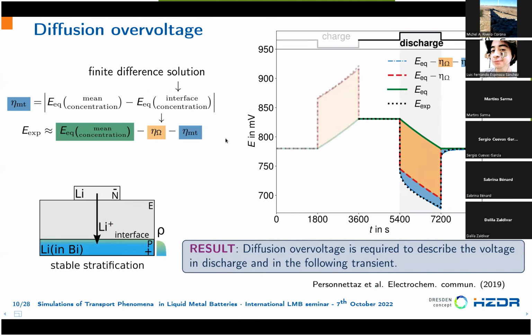Now, if we take the previous model and plug it inside our mass transport overvoltage equation, we see that we are able to capture extremely well the experimental behavior. So the three contributions, the equilibrium, the ohmic, and the mass transport, are able to describe perfectly what happened in the experiment. They are also able to describe the following transient. When the current is shut off, there is a concentration profile that has to go to the homogeneous distribution, and this is what we see here. So diffusion overvoltage is required during discharge.